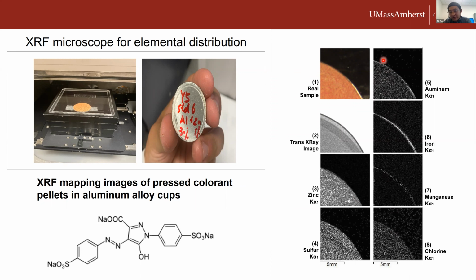Very interestingly, we have this ring structure, and this ring is actually coming from the metal cup that is holding the sample. We can easily know that this is an aluminum alloy that has aluminum, iron, and manganese in it. Also, we can see the aluminum distribution in this sample is very good. It's very evenly distributed. Whereas if you look at the zinc, it's not that well distributed. We have scatter here and there. We have some high concentration of zinc here, some low levels here. In the meantime, we can also look for some other compounds such as sulfur and chlorine. The yellow 5 molecules inherently have sulfur in them.